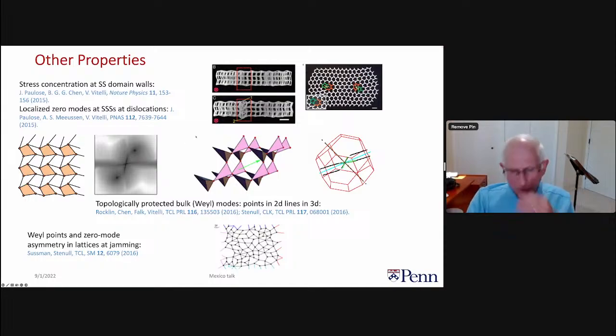Okay, so just to cover a couple of other things that happen. This shows us a lattice that has the Weyl modes, and you can see here in the density, in color or darkness intensity, the closer you get to 0, the darker the intensity is. So these are 2 zero modes, and you have the acoustic phonons coming in like this, and they have a peculiar property that their frequency goes as q squared near the origin there.